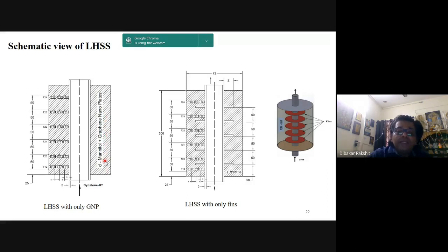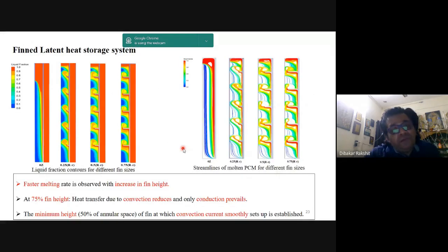So in combination, in different concentrations, graphene nanoplates were introduced in this phase change material, and then we introduced fins into it. We tried to see how the effect of graphene nanoplates over the phase change material and the effect of the fins can be utilized to design a perfect thermal storage battery for this particular application of green air conditioners. So these are the CFD analyses which we have done.